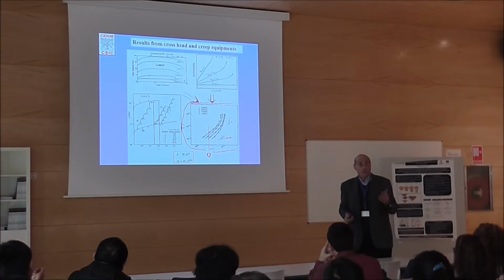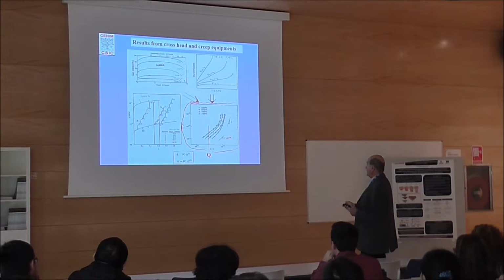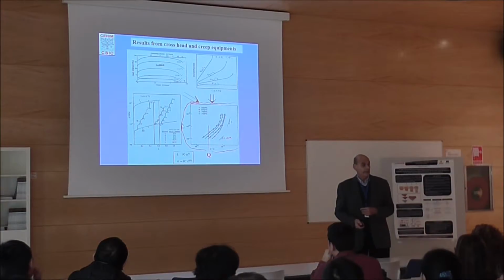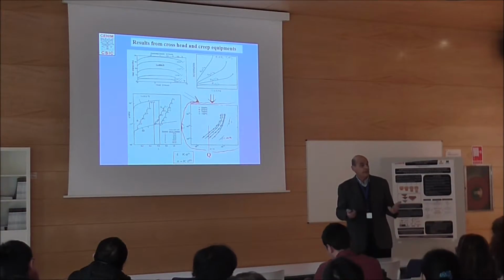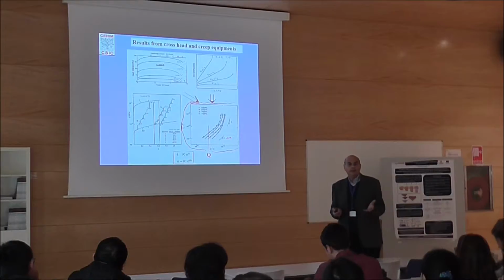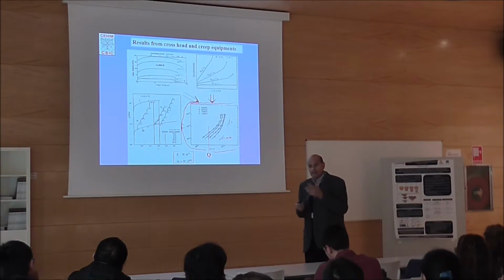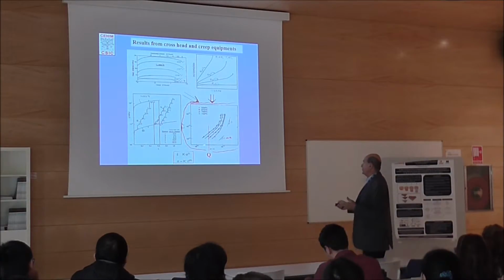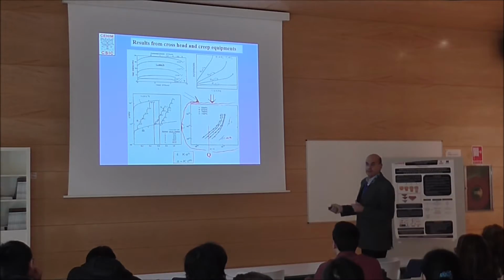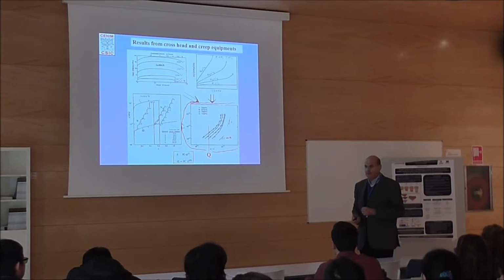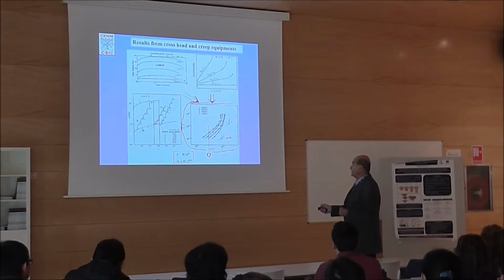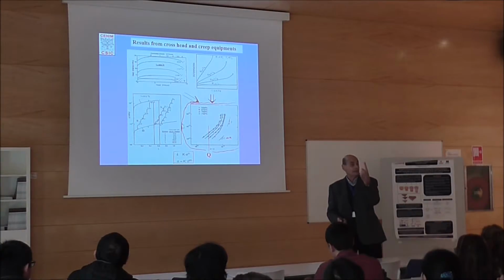There is another way, because here you need 1, 2, 3, 4, 5, 6, 7 samples. We can simplify this, and experimentally we can determine the stress exponent very simply, just by varying the strain rate during the test. So you can trust this. There are different ways. By just changing the strain rate, we can obtain the whole curve in one sample. So one sample, one set of values.